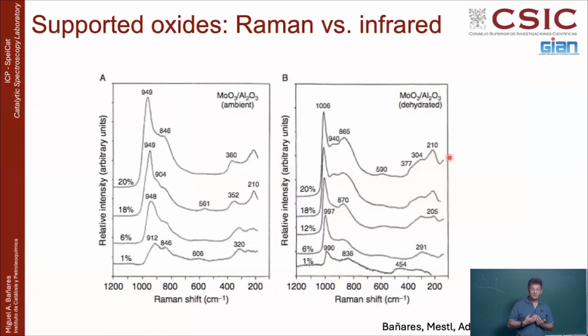Now, for me, typically working with supported oxides, the main problem is that what I like, what I love, and what I really get the maximum amount of information of a supported oxide is in this region below 1000. Here you have the Raman spectrum of the supported molybdenum oxide on alumina. This catalyst was like, there you have from 1 to 20%. You can see 1% at the bottom. You can see the things very nicely. 99% of the sample is alumina, not a problem. You can see these bands. Of course, the spectrum looks different. Raman, like infrared, is very sensitive to molecular changes. If the catalyst is under ambient conditions, it will be hydrated.